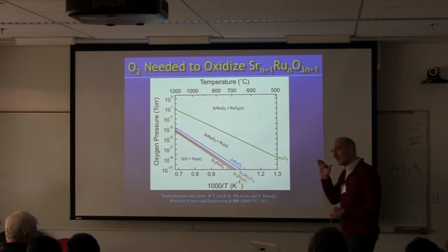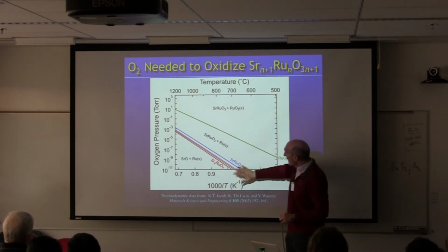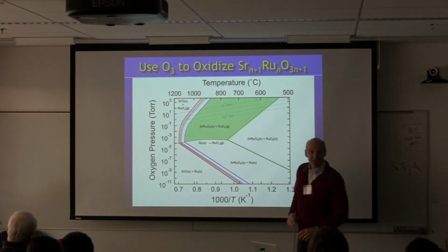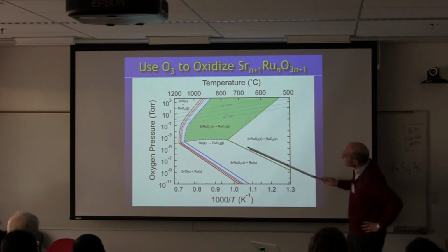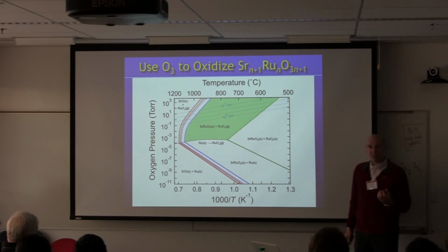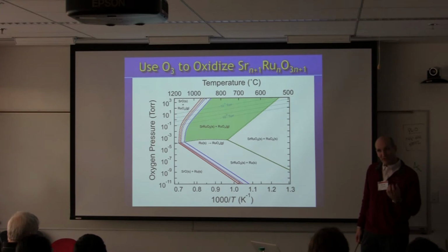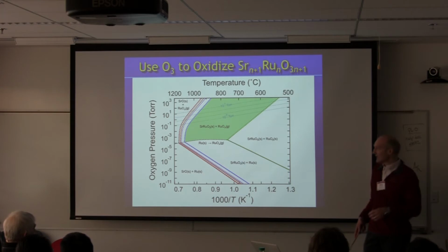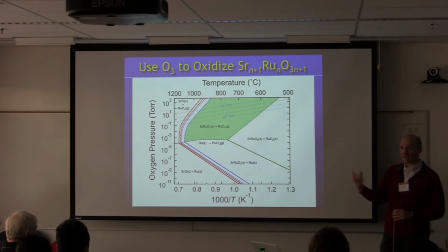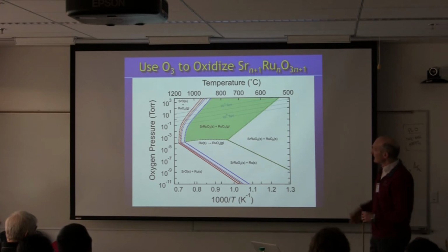Okay, but now let's take it to the next step. So far, I've shown you what happens in a closed system. So here, I don't have volatility of the ruthenium, but let's add a more sophisticated thermodynamic calculation. So this is what I showed you a second ago. Let's now look at the gas phase and make it an open system calculation where I'm allowing ruthenium loss as ruthenium oxides in the vapor phase. So I'm deliberately supplying an excess of ruthenium from my metal source, ruthenium metal, 3 times as much ruthenium, in fact, in this thermodynamic calculation, and allowing ruthenium oxides to volatilize.